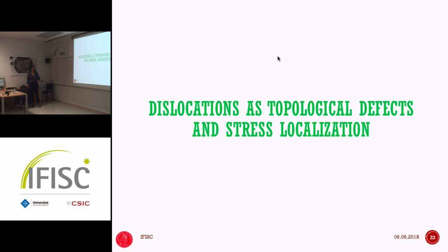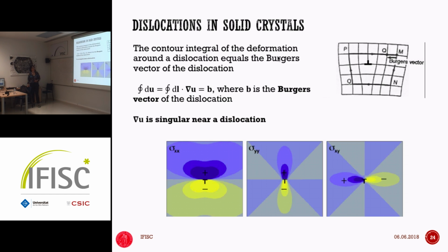Okay, so let me tell you a little bit about the defects in crystals and how they are related to topological defects, and that they actually are stress localizers for this particular definition of the stress field. So let's go back to classical elasticity, where a dislocation is defined as a singularity in the mechanical response. If you look at the stress fields in linear elasticity, you have a singular behavior. The stress field diverges at the dislocation, but it's also asymmetric. For example, if you look at the compression stress, sigma xx, it has a compressional stress above it, and it has an extension, negative stress below it. The definition of an edge dislocation is that you insert an extra plane somewhere. And it's a topological defect because all the affine transformations that before you could do no longer hold.